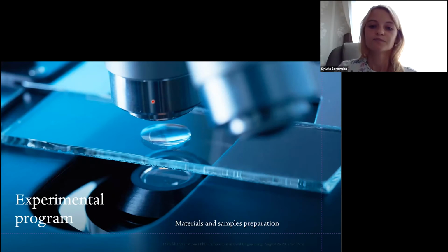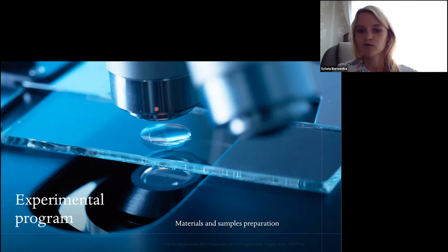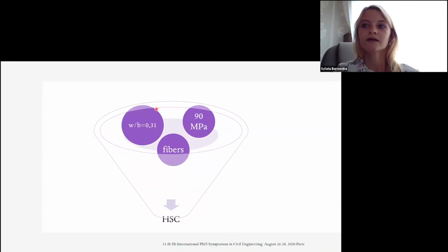Let's turn to my experimental program. The test was carried out on concrete with a compressive strength of 90 megapascals in order to analyze the effect of addition of fibers to high-strength concrete on their resistance to cyclic freeze-thaw. Steel and basalt fibers were used. In all series, constant water-binder ratio was provided.